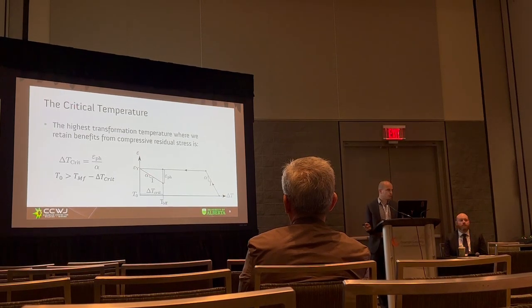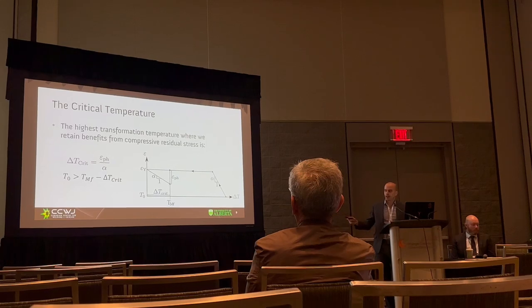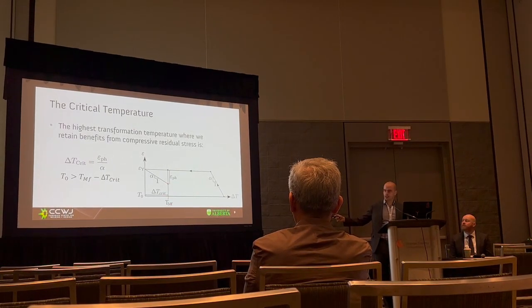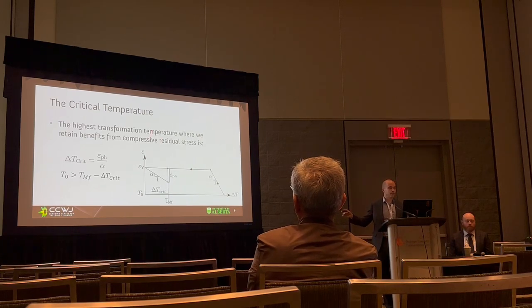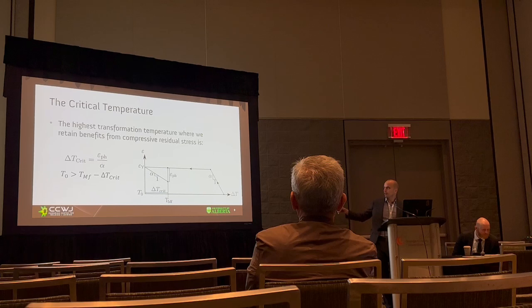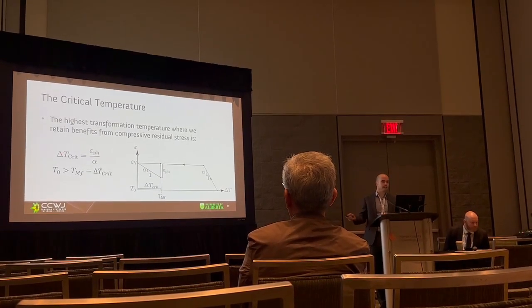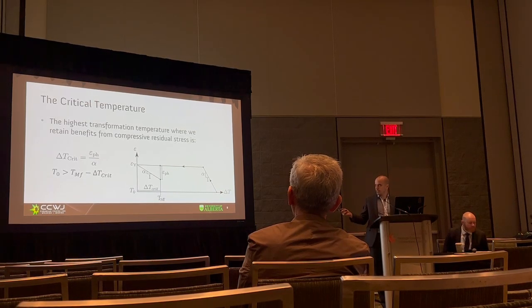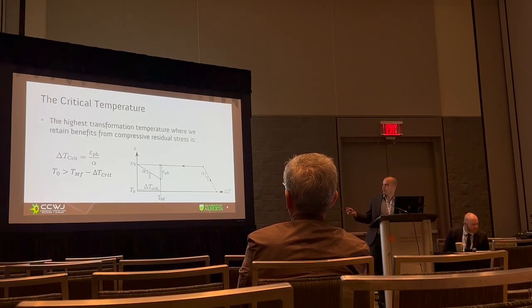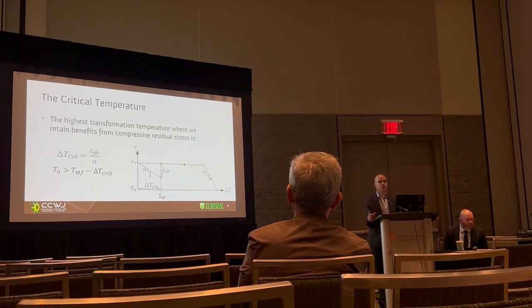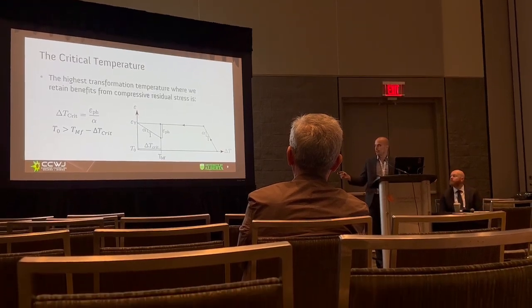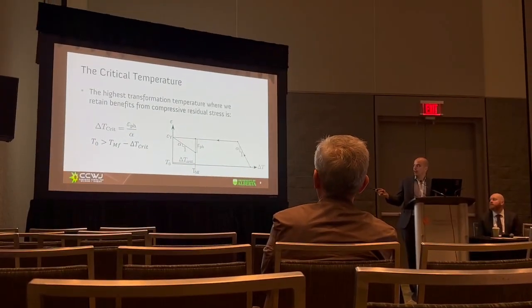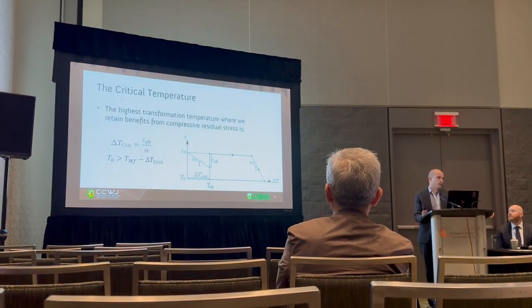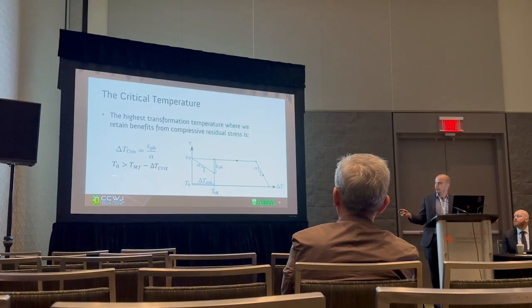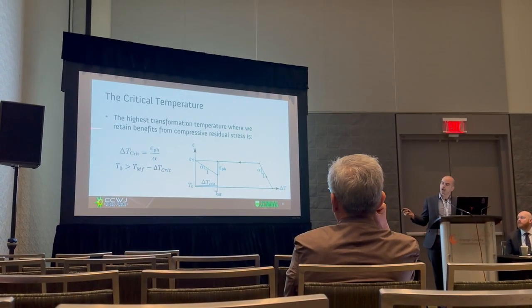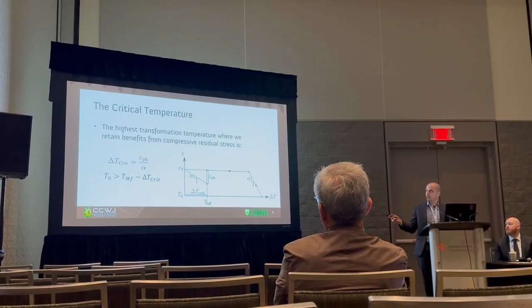If it's just based on this recontraction cooling, which was the thing we decided to try looking at, maybe that's all it is. Then what we can establish is that if this is the temperature the martensite transition finishes, all I have to look at is how much phase strain was there, how much phase expansion occurred as a result of the martensite transition, and then at what rate does it recontract until we hit tension again. From just looking at this, we can get a really easy answer. If this is the amount of phase expansion we have, which is easy to get, it can be simulated in JMatPro, you can find it from a Satoh test, it's also a known value for lots of materials, and I know my thermal contraction coefficient, then I know exactly, if I want to retain some of this, if I don't want tensional residual stress after my weld has reached equilibrium temperature, I just need my equilibrium temperature to be higher than the martensite finish temperature, and this thing I call delta T crit, which is just the ratio of the amount of phase expansion to the thermal contraction coefficient.